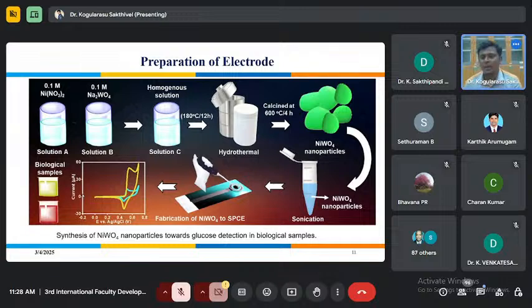Then it was again sonicated because there must be some clumsy particles, agglomeration or aggregation in that nanoparticle, so that after sonication it is dispersed to make it a homogeneous thing, and we fabricated the electrode on screen printed carbon electrode. So here we have seen the final result. This is the thing we are going to use as a strip for sensing glucose.